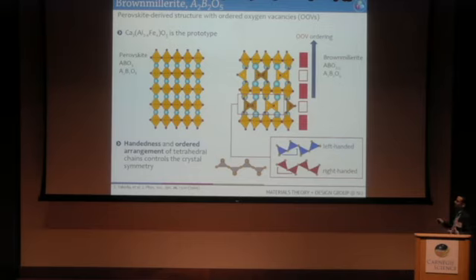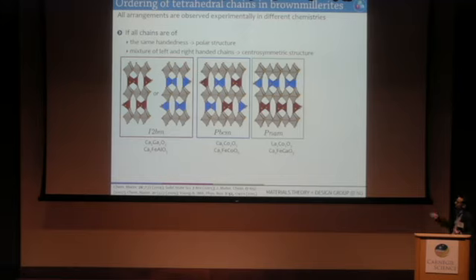So experimentally, just like perovskite, there are many compounds which exhibit the brownmillerite crystal structure. I'm going to show you some of them on this slide. And I've kept the tetrahedral chain ordering coloring the same so that you can see the difference. There are brownmillerite structures which are polar. They look like this. And in those cases, you have a single type of chain. They're either all left-handed or all right-handed in every alternating layer like this. Then there are two other polymorphs which preserve inversion symmetry. You can think of these as having essentially a 50% mixture of left-handed and right-handed tetrahedral chains, and they can be exclusively in one layer or the other, or they can be mixed within the layers. And that will dictate whether you're in this orthorhombic space group or that orthorhombic space group.